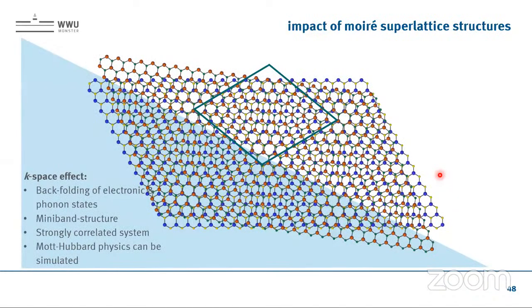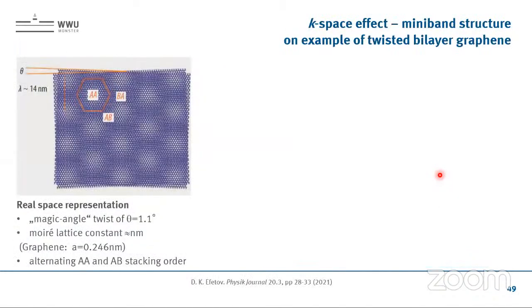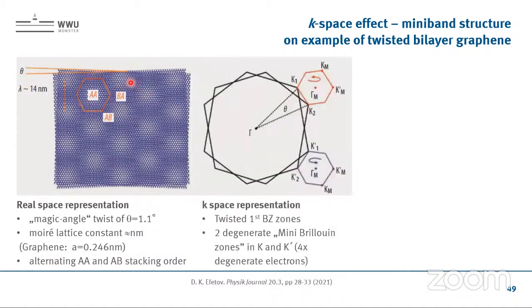And another direction, the K-space effects, is such that you can see again this lattice has a high periodicity. And if you go back to your textbook knowledge, what happens if you have a periodic lattice? You do the Bloch ansatz, you have a periodic part in your wave function, and you do the Fourier transform, you go to K-space, and everything can also be done here. So meaning you can also do the same for this moiré potential with this long wavelength. With that you get a so-called mini Brillouin zone, superimposed to the large one.